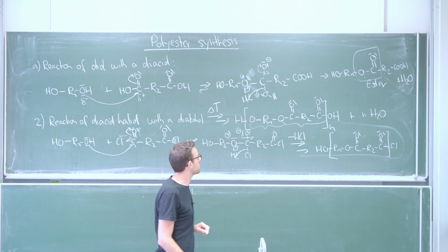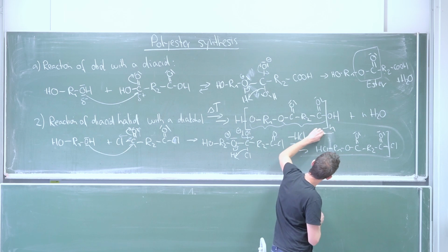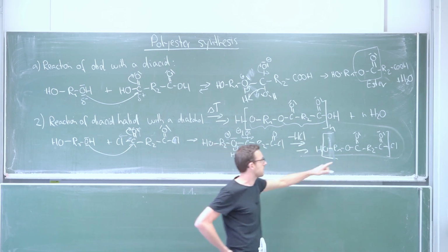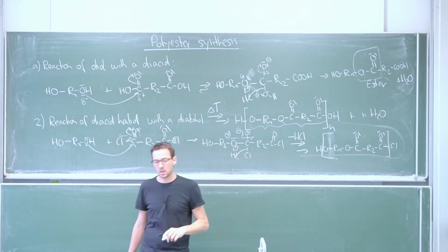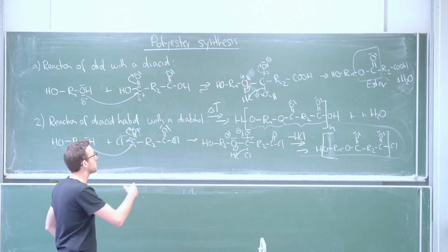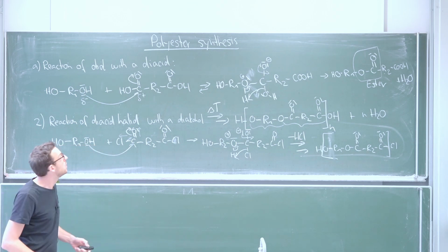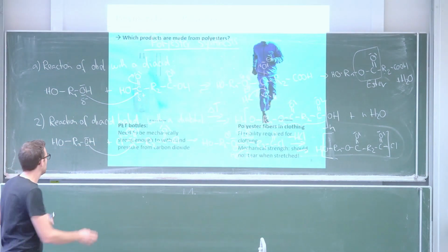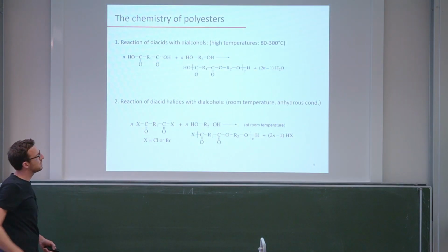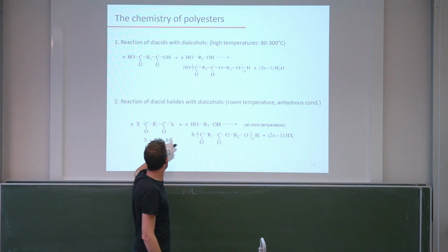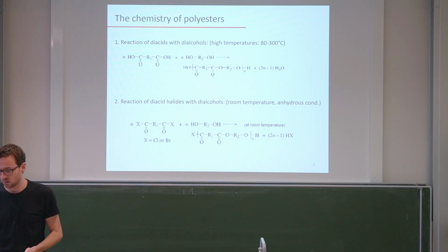a reaction that you actually don't really see. Oh, sorry. Now you don't really see anymore that you had this acid halide, except for here this end group. So you see, and you need to remove HCl. So very simple chemistry, and what we do is, as we said, literally link one molecule after the other. Here you see this again in black and white. And the second reaction, because we release HCl, which is a gas, we can conduct at room temperature.